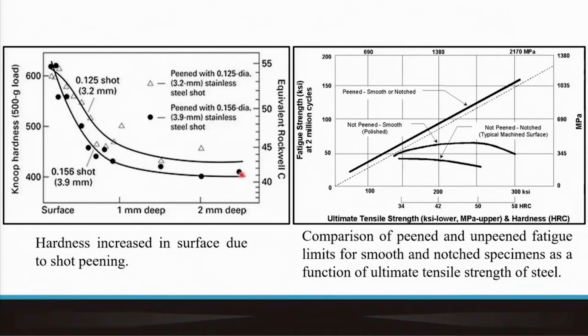The reason is very simple: with bigger diameter, the mass is higher, and hence the impact energy, or the energy that you are able to transfer at the point of impact, is higher. So the degree of straining is higher, and hence not only is the hardness higher, but it actually penetrates to a deeper region. Now, let me also mention that this is about the depth, but when you are using smaller diameter, then the penetration is shallower. So the hardness retained on the surface is higher.